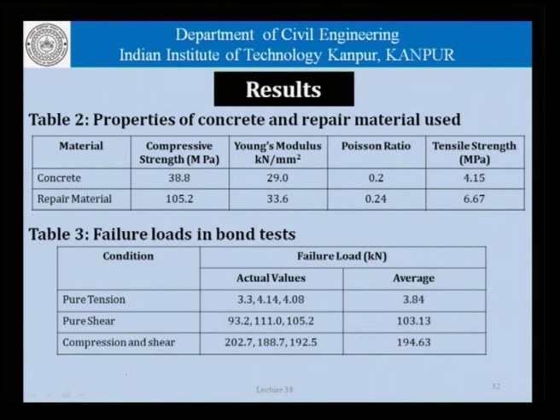These are some of the results which have been obtained from the pure tension, pure shear, compression and shear values for different surface preparations. The values are different, and of course, these are the results for the compressive strength, Young's modulus, Poisson's ratio and the tensile strengths of the individual concrete and the repair material. So, you can see that the compressive strength of the repair material per se is much higher than that of concrete, but the Young's modulus, the Poisson's ratio and the tensile strengths are not so much apart.